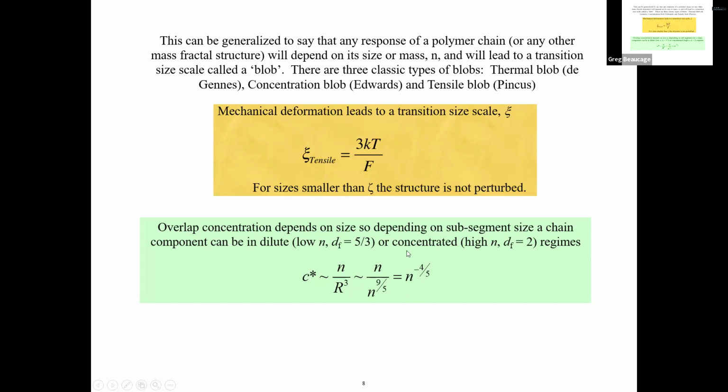And if you go to larger n, the coil is a random walk, like a collapse of a Gaussian coil, a theta coil. Right, so you go expanded at small scale, and then Gaussian at large scale. So on a large scale, it's dense. At a small scale, it's expanded, which is kind of hard to visualize.